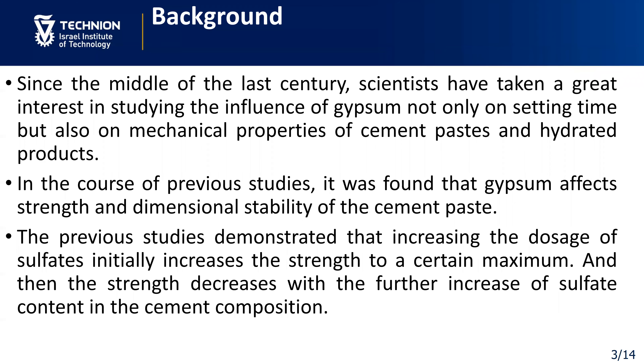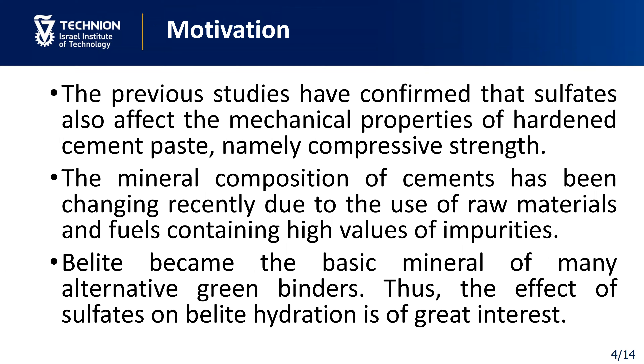Since the middle of the last century, scientists have taken a great interest in studying the influence of gypsum not only on setting time, but also on mechanical properties of cement-based hydrated products. In the course of previous studies, it was found that gypsum affects strength and dimensional stability of the cement paste. The previous studies demonstrated that increasing the dosage of sulfates initially increases the strength to a maximum, and then the strength decreases with further increase of sulfate content.